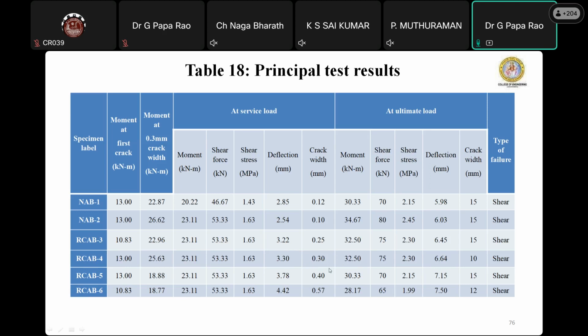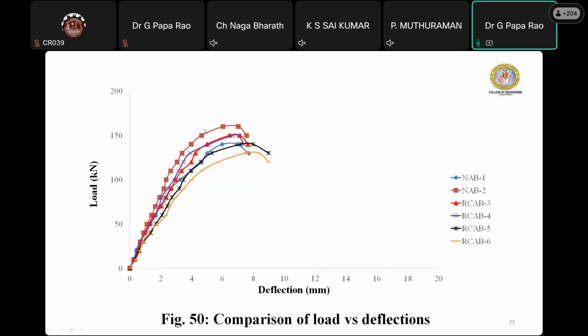If you look at the other two beams, RCAB5 and RCAB6, the induced crack width is beyond our permissible limit for RC members under cracked sections. Similarly, for crack width 0.3 and deflections, if the replacement is beyond 50%, our deflection values are again slightly increased. So with our experimental observations, these are the load carrying capacities of all 6 different beams.